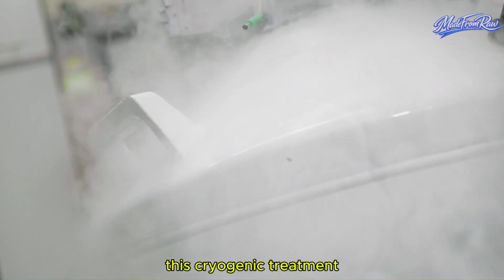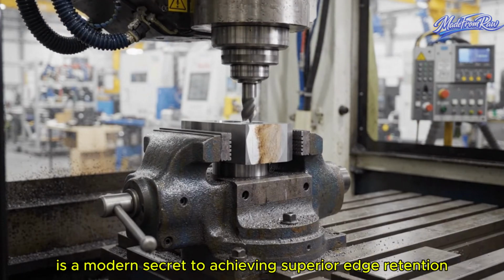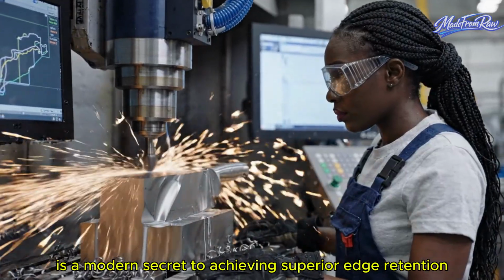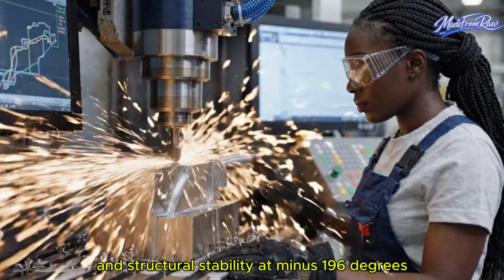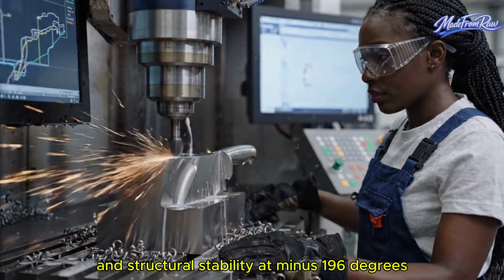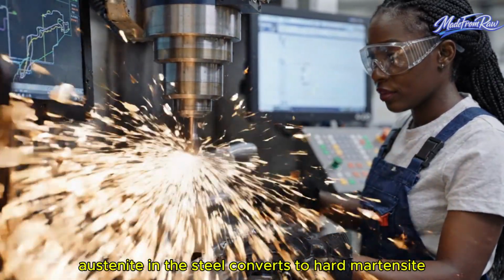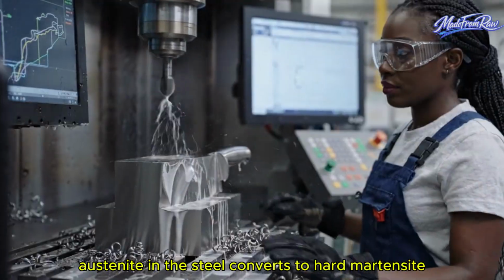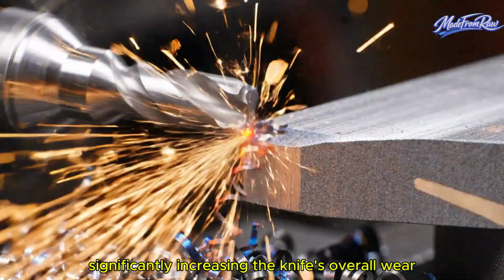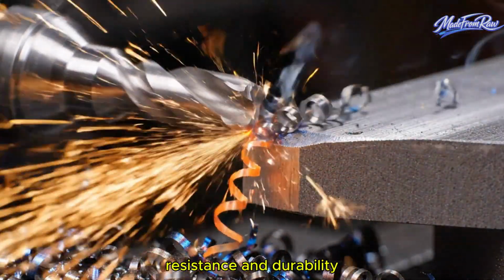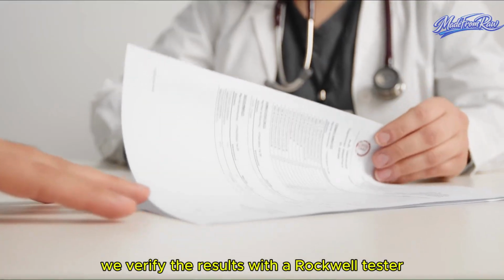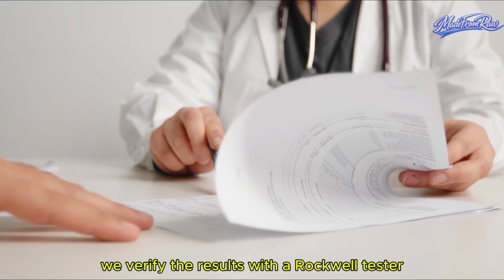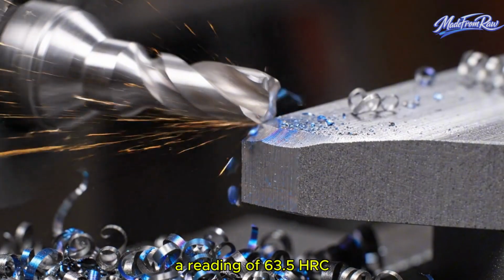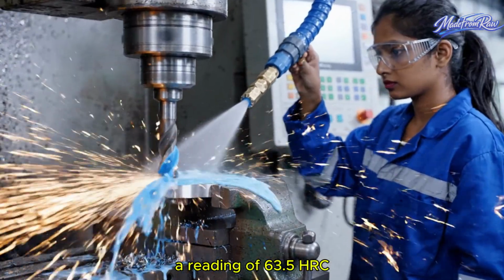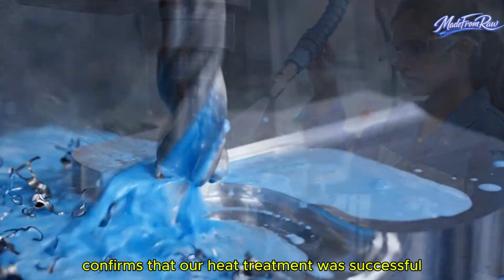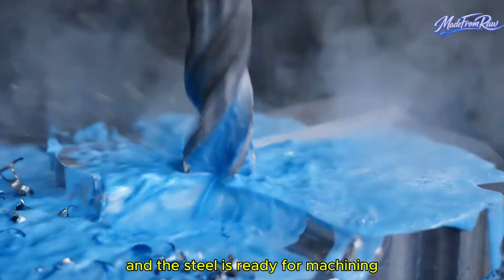This cryogenic treatment is a modern secret to achieving superior edge retention and structural stability. At -196 degrees, the remaining austenite in the steel converts to hard martensite, significantly increasing the knife's overall wear resistance and durability. We verify the results with a Rockwell tester. A reading of 63.5 HRC confirms that our heat treatment was successful and the steel is ready for machining.